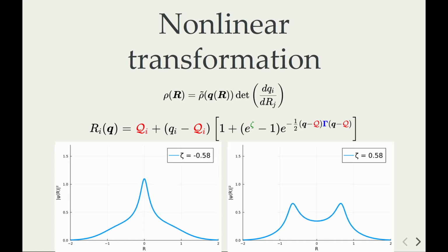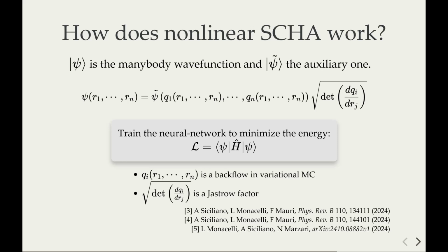So if we take a transformation like this, very ugly, what happens is that by changing one of the parameters, like the z in this equation, we are actually changing the Gaussian into something which is not a Gaussian anymore. And the nice thing is that we can stack multiple transformations one after the other, and this is actually a neural network. So how does this method work, essentially?